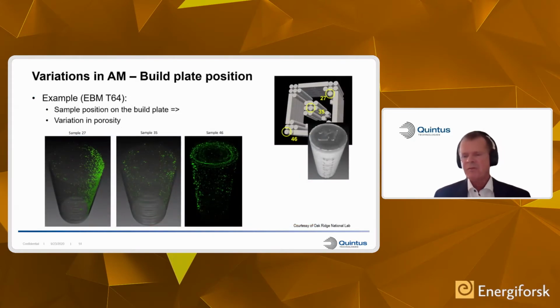Also, what we can see is that positioning on the build plate has an effect on the porosity. And this is something that we've seen in tests together with customers. One way of reducing the scatter or variation in porosity is to perform a HIP afterwards, where you can completely remove all the variations in porosity.